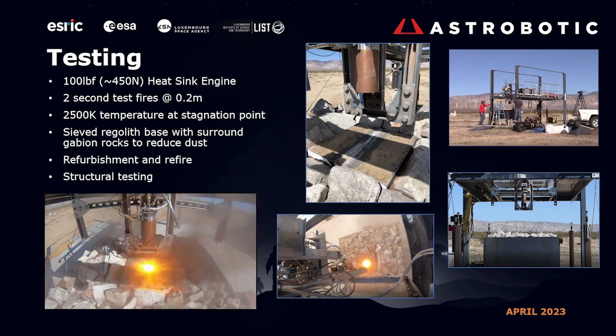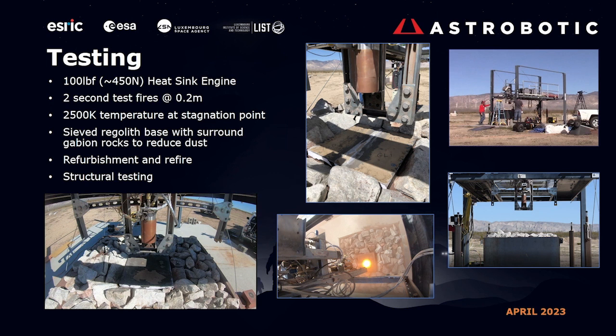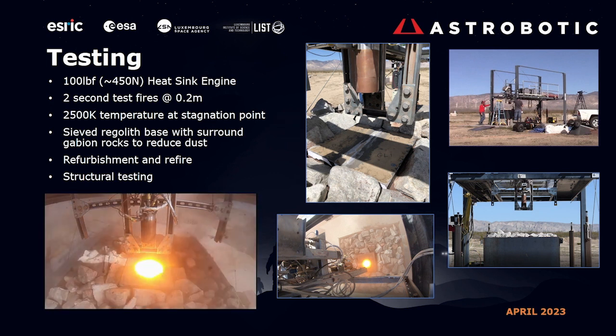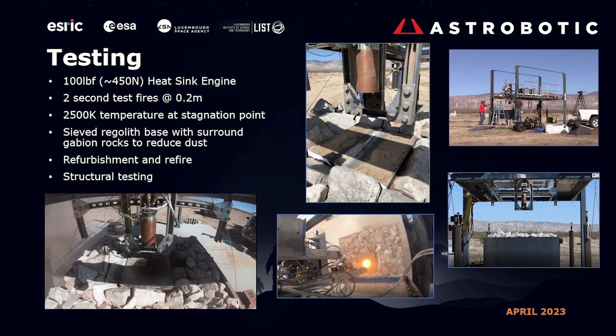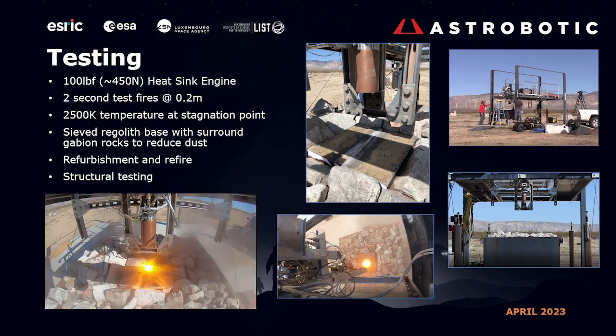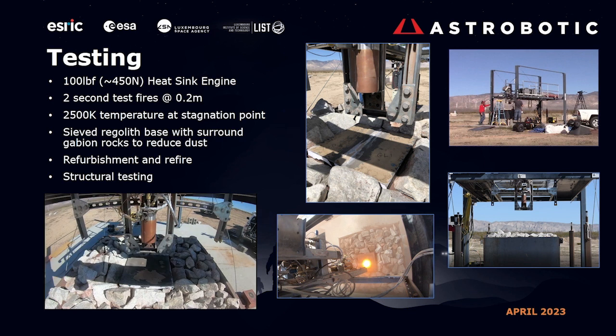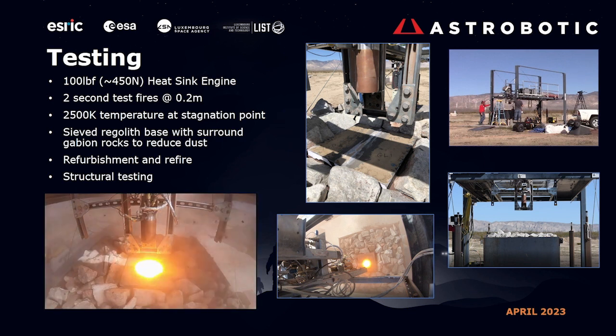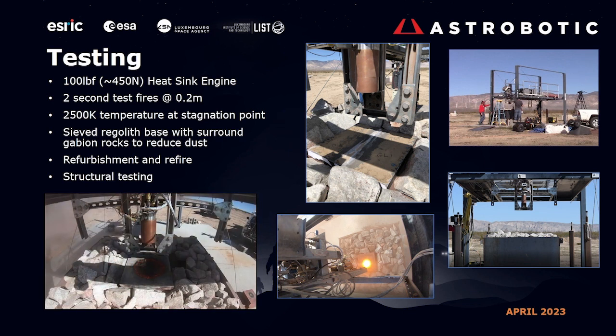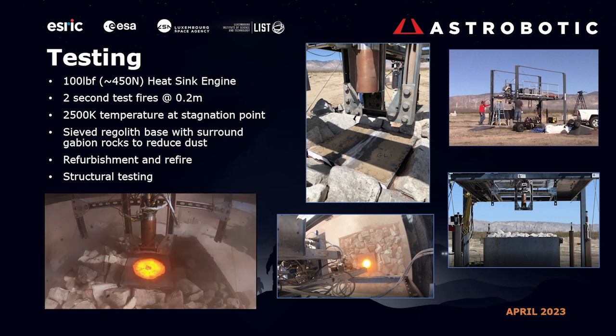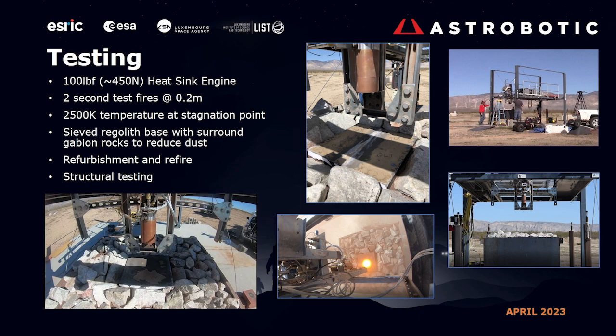And in the animation, you'll notice that there's large rocks around the pad. That's just to keep everything in place for the testing. But underneath that landing pad, there's actually a large container of regolith fines, that regolith simulant fines. It's a medium to high fidelity regolith simulant that we're using, and that's to see what would happen if we did have burn through on any of these pads.